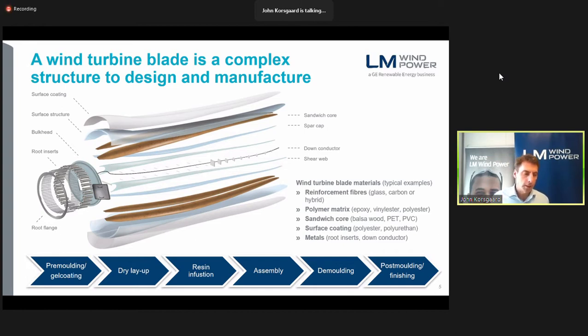If we look at the manufacturing process, at a high level, it's 6 process steps, with pre-molding, gel coating, where the molds are prepared for molding and the surface layer is applied into the mold. Then we have the dry layup, where all reinforcement, core material and other materials are applied into the mold.